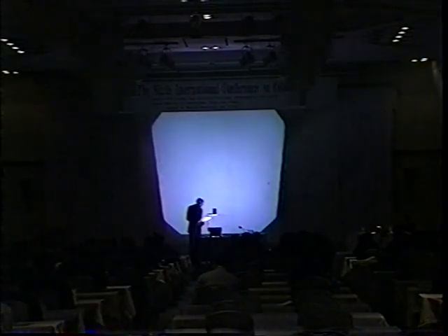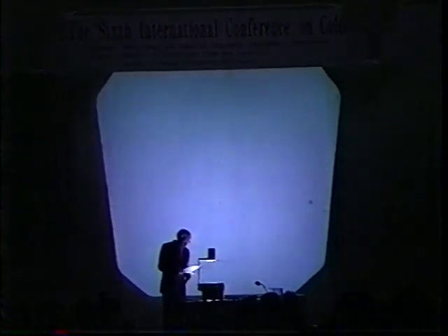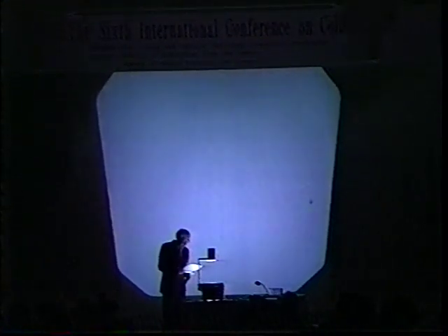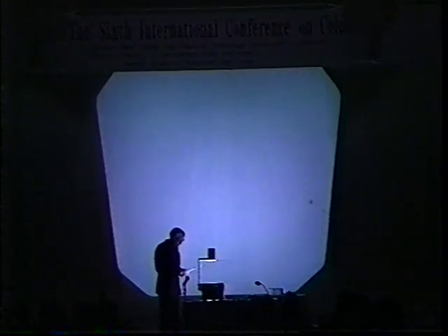The tritium generation rate for a sample of polycrystalline molybdenum, at use of a discharge of protium with a major concentration of deuterium, decreased from the maximum value for deuterium and was established at a level of values an order exceeding background ones. The time to achieve a satisfactory value of tritium generation rate exceeded 200 hours.